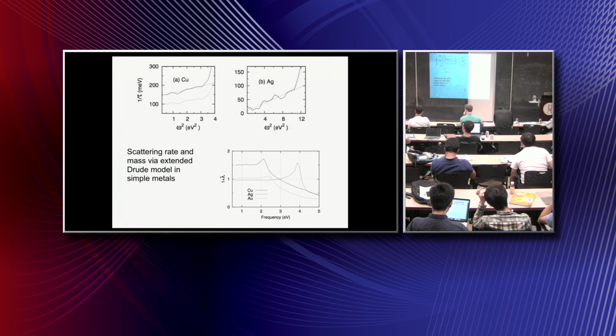And 1 over tau allows you to think about a frequency-dependent scattering rate. So if I imagine a 0 frequency excitation of the system, there's not very much it can interact with, right? As it moves along at something infinitesimally close to 0, it can bump into static disorder, but it can't excite any real excitations of the system. Imagine an electron moving along, and it cannot scatter off and make a real excitation, it cannot make an optical phonon. Imagine I have an optical phonon of 20 millielectron volts. If I inject 1 millielectron volt into the system, it doesn't have enough to create an optical phonon.